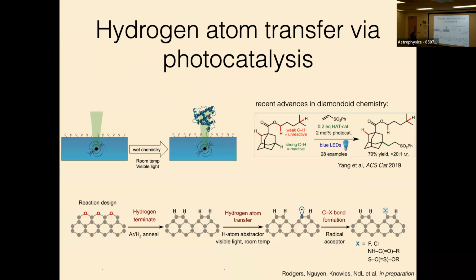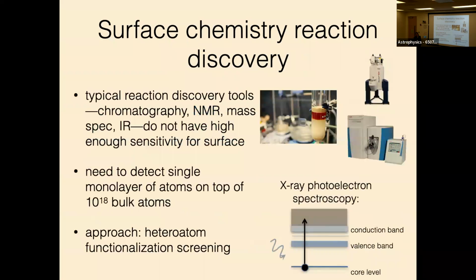So the general scheme here was that we start with our oxygen terminated diamond, we convert it to hydrogen terminated diamond, we do this hydrogen atom transfer, and then we put something on the diamond surface. And the nice thing is this is all at room temperature with visible light. It's in very, very gentle conditions. Okay, so this was basically Rob Knowles' idea. He didn't think it would take that long, and I said, well, lots of people have been trying to functionalize diamond for like half a century, so I don't know why you think this will be so fast. But Rob is a genius, so it went really fast.